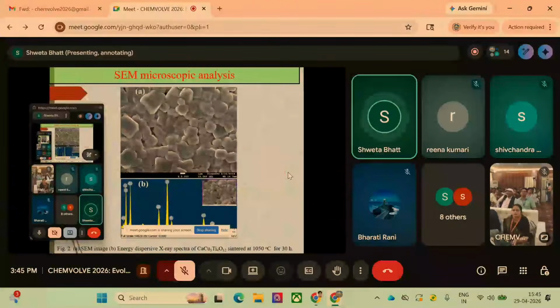Here we have determined the morphology and also confirmed whether the material is pure or not. For that purpose, we have used scanning electron microscopy. For that, we have used a pellet to show the morphology. In the pellet, we have seen that there are two types of grains inside the morphology. Some are very large in size and some are very small in size.